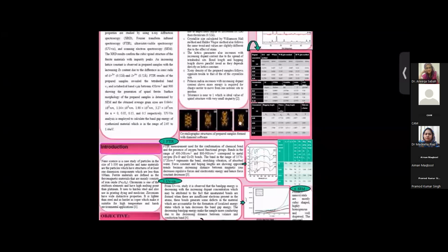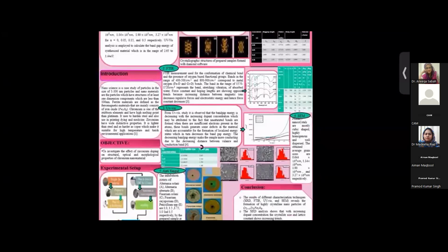FTIR measurements were used for the confirmation of chemical bonds and the presence of oxygen-based functional groups. The bands in the range of 400 to 500 and 800 to 900 per centimeter correspond to metal-oxygen bonds, and the band in the range of 1570 to 1720 per centimeter represents the bending vibrations of absorbed water. Force constant and hopping lengths show opposite trends because increasing distance between the magnetic ions decreases repulsive forces and magnetic and electrostatic energy, and hence the force constant decreases, as shown in this table also.